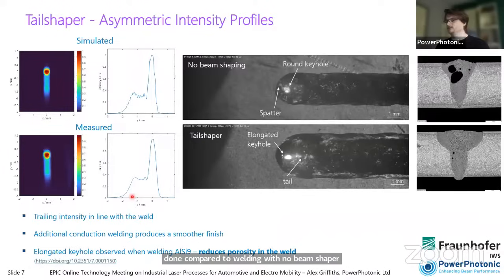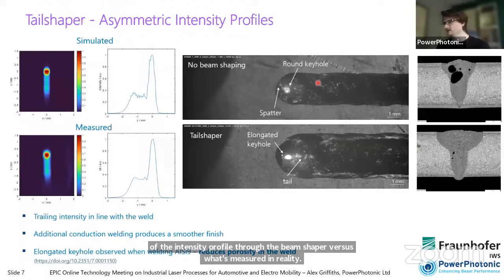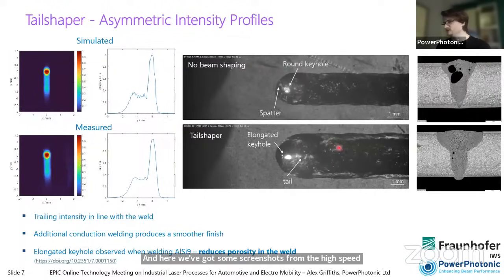Moving to something more unique to us, we have this tail, what we've been terming the tail shaper output. So this is an asymmetric beam that's been tailored to match the asymmetric nature of the welding process. So we have this linear shaped spot that would translate in the direction of the weld. You have this high intensity spot here that's still generating the keyhole and performing the weld, and a lower intensity tail that follows it behind. Again, we've got good agreement between what we simulate of the intensity profile through the beam shaper versus what's measured in reality. And here we've got some screenshots from the high-speed video of where we have no beam shaping, you get this round keyhole. And with the tail shaper, you get an elongated keyhole and a trailing tail behind it.